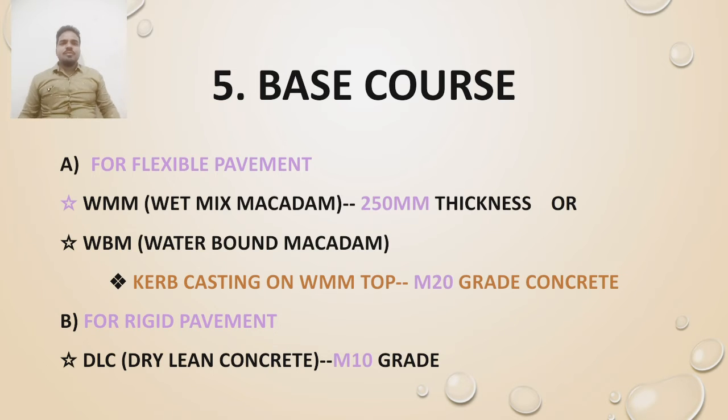WMM means wet mix macadam, which is well mixed, clean crushed and well graded granular material and stone dust with a sufficient quantity of water in a mixing plant. WMM is laid in two layers of total thickness 250 mm. The minimum thickness of a single compacted layer must not be less than 75 mm.